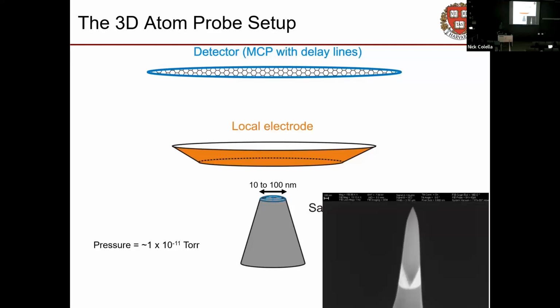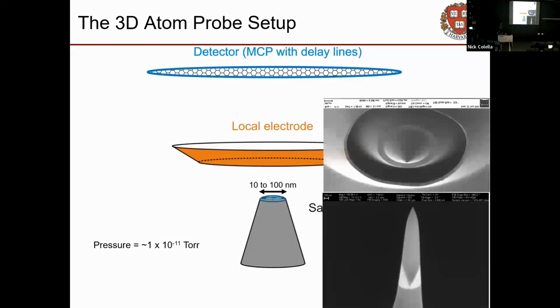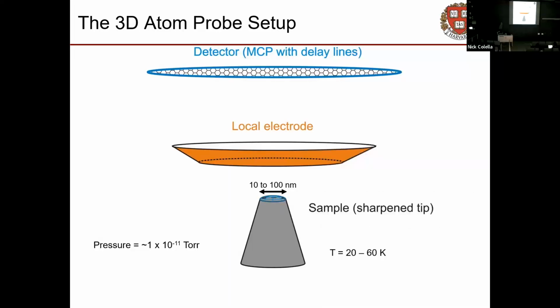We put it under a hollow cone-shaped electrode. They look like this. We cool it way down. This sample's at like 20 Kelvin. Why has it got to be so cold? It's got to be so cold because heat means things are moving. Heat means that the atoms in your piece of material are buzzing around. And we want to actually get a measurement of where the atom's supposed to be sitting. And if they're all buzzing around, they don't have a very meaningful center position. Our spatial resolution goes down. So we cool it so they all stop buzzing around, hold still, and get a good look at them.